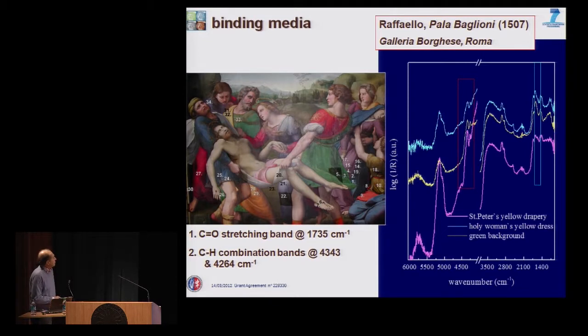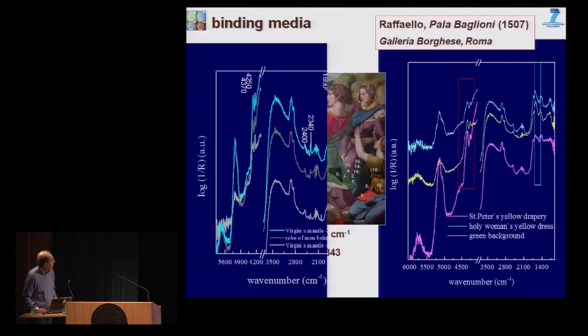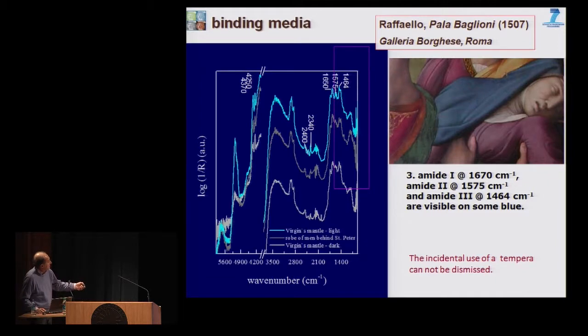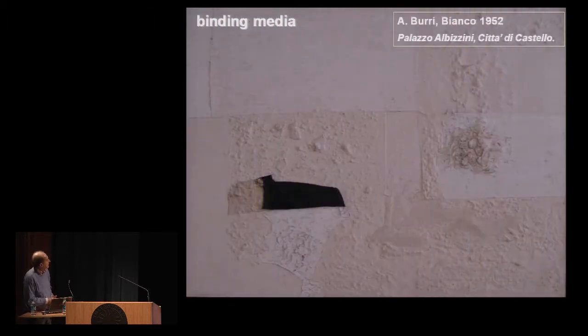FTIR gives good results concerning the identification of the binding media. Good in the sense that, the measurements being non-destructive, you can determine the family of belonging of the binding media. So you can determine if it is a protein or a lipidic binder. Like in this case, this was painted by Raphael in oil, although in some regions the presence of some proteinaceous binder was detected on the blue mantle of the Virgin. Maybe some proteinaceous binder was used with the first layer of azurite, and then the ultramarine blue was layered there.